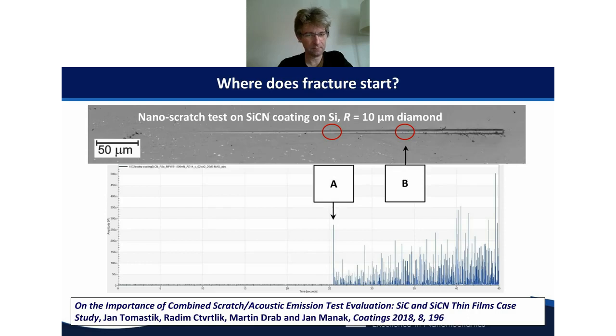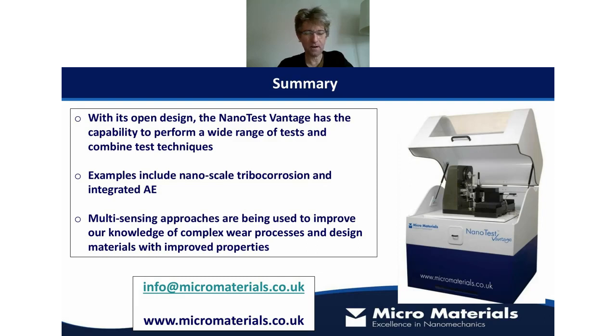And indeed the researchers there did a focused ion beam cut at that point, and they exactly pick up the subsurface crack that is responsible for the start of this acoustic emission. So it's a very sensitive type of test. So hopefully that's given you some flavor for some of the other things that we mean when we talk about multifunctionality in the system.